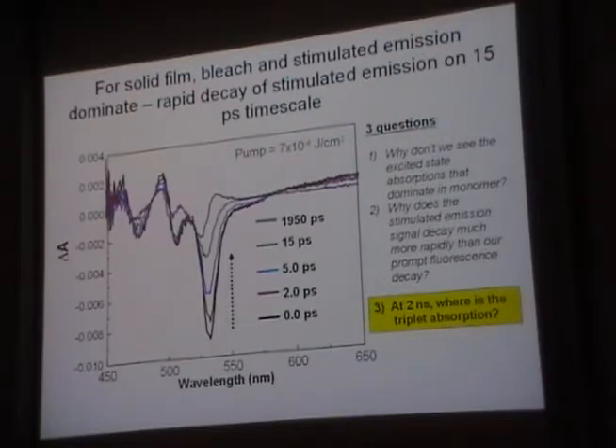There's some funny business going on out here, but all of a sudden we get a big negative signal. All of those excited state absorptions that were so pronounced in the singlet don't appear here, and we're left wondering what's going on. But the one thing we know that's not going on is we don't see a big triplet absorption growing up here. So maybe our whole idea about exciton fission was completely wrong. And that would be very disturbing, okay?